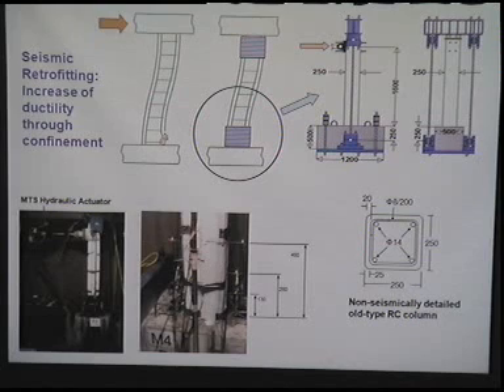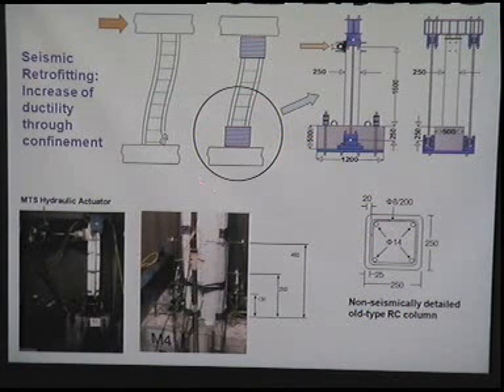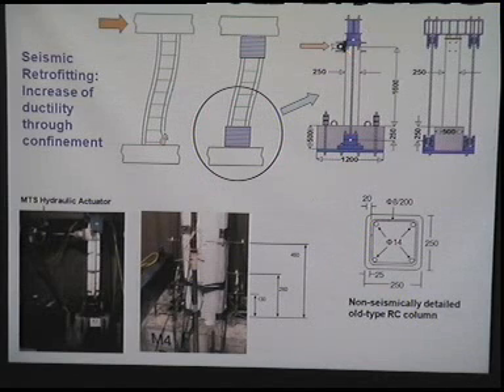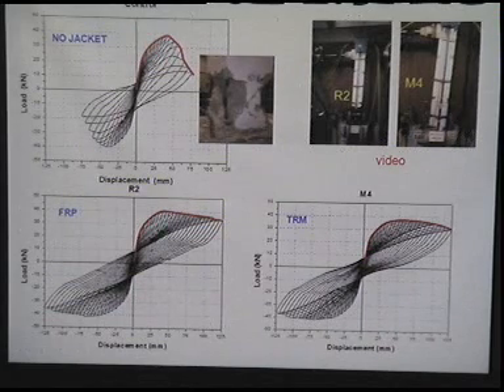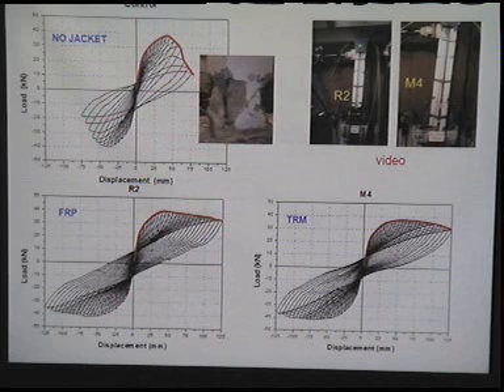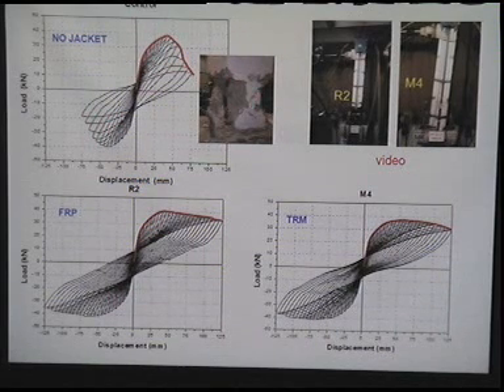The next step was to verify exactly the same failure mechanism in larger scale members. We tested columns, full scale columns, cantilever type specimens subjected to horizontal displacements to simulate the effect of earthquakes. You can take a look at some photographs here. So those specimens were confined only at the bottom with FRP or TRM jackets. I have some results which illustrate how the control specimen, the control column, that is the one without jacketing, behaved.